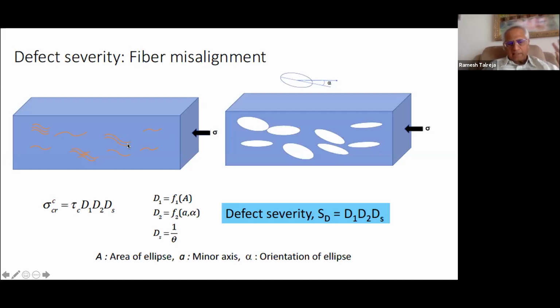So inspired by some fracture mechanics analysis, I said, let's smear these together as ellipses, like an area of influence, and then put those ellipses in a solid and consider these to be sort of elliptical cracks. Of course, they are not cracks, but you use a similar idea as if these were cracks. So I constructed a measure of defect severity with three parameters in it. Two are the smeared out ellipse characteristic values, area of the ellipse, the minor axis length and orientation of the ellipse, and then the maximum misalignment angle within the ellipse.